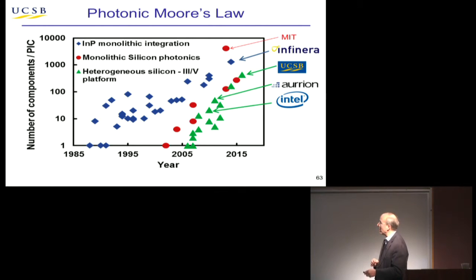So the blue is all of the best integration results on indium phosphide. And a bunch of these data points are Infinera, but certainly the highest one here, that's our 2.2 terabit per second transceiver. The red dots here are the biggest level of integration. So this is number of devices integrated on one waveguide. You can always have parallel waveguides and get more numbers, but these are numbers integrated on one waveguide. And so MIT is actually highest. This is Mike Watts' work on his LiDAR chip. But several thousand devices, and actually higher than the biggest indium phosphide chip.